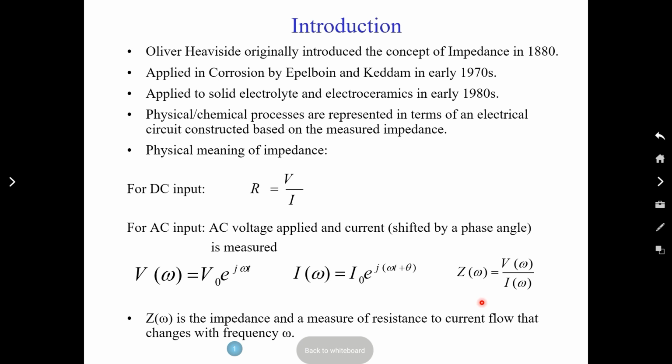How do you know whether you have captured everything? From the AC measurement, you will get all these components, the contributions from grain boundary one, grain boundary two, the grain, etc. You just add them up, and the total resistance should be exactly equal to the DC resistance.